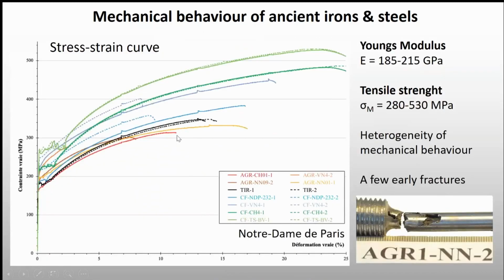So here are the results of this testing, with typical stress strain curves on the samples of Notre-Dame. The AGR samples are here in red, orange, and yellow, the TIR is in black, and the CF samples are in green and blue. So we can see the typical stress strain curve, you have the elastic domain here and then the plastic domain. There's a real heterogeneity of mechanical behavior, as all the curves are really different. The Young's modulus is that of iron, about 200 GPa, with not much difference between the samples.